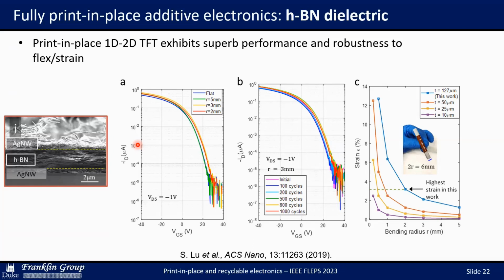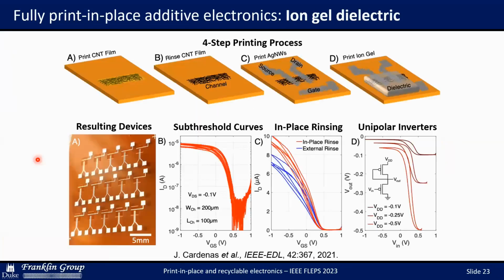performed quite well. One of the biggest challenges to this whole approach is to keep these subsequently printed layers from causing intermixing with the former layers. Because all of these are ultimately solution compatible, there has to be a way of keeping those from just meshing together after the print. And so we did that with different additives into the inks and establishing the right type of print sequence. We've also done this with an ion gel as a dielectric.